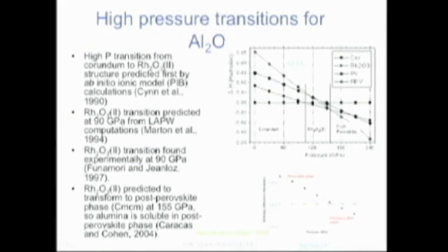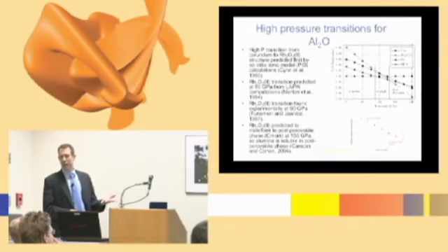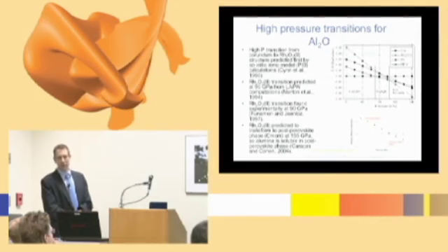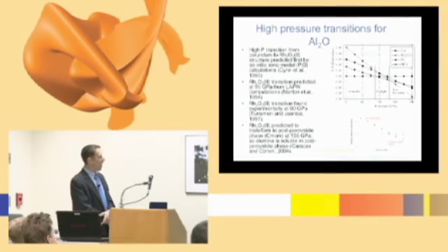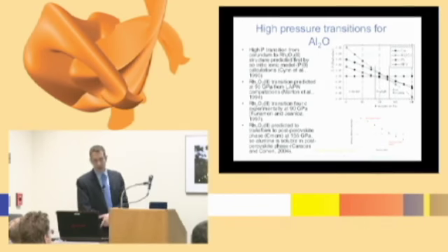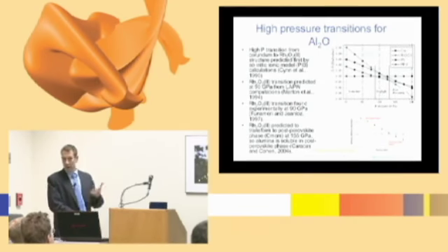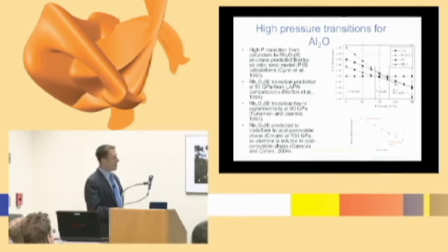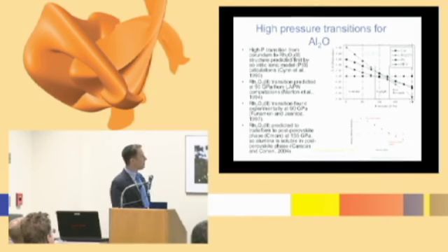Not only were they observed to be qualitatively correct, but within really 1 or 2 GPa of the predicted transition pressures. So to tell you the truth, it's hard to even make such accurate predictions with QMC just because of numerical issues, not because of anything fundamental. But with DFT, one can do the numerics essentially perfectly, and it's accurate enough to predict these kinds of phase transitions.